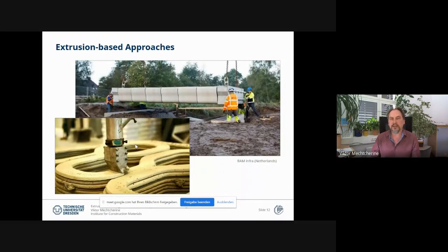These are segments which are printed separately and then put together, and obviously the colleagues use pre-stressed steel to reinforce the elements. So in this case, you see that, other than the two other examples, the nozzle is not circular, but rather rectangular. And in this case, the nozzle rotates with the changing direction of the printing.